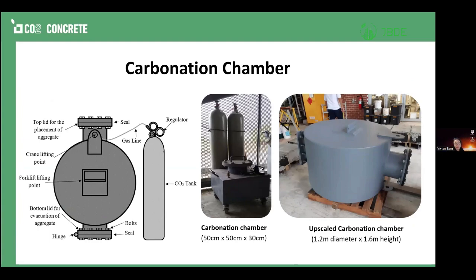It's about 50 centimeters by 50 centimeters by 30 centimeters, which is really just a small black box. You can put only about 50 kilograms of aggregates in. But in 2018, because we had slabs to pour for the universities, which required a larger amount of materials, that's why at that time we produced a commercialized scale carbonation chamber.